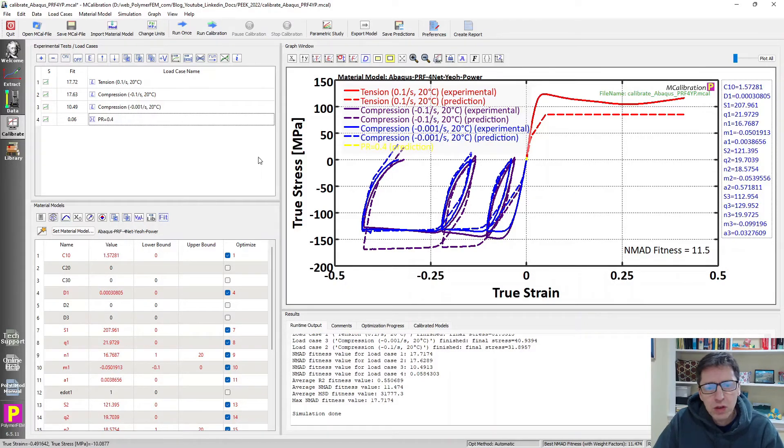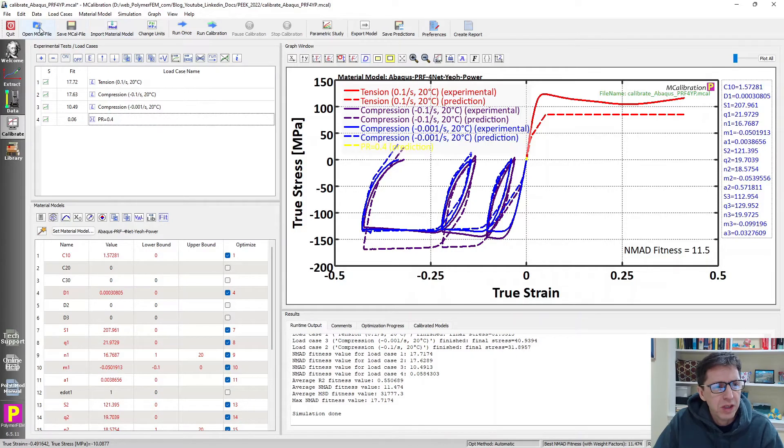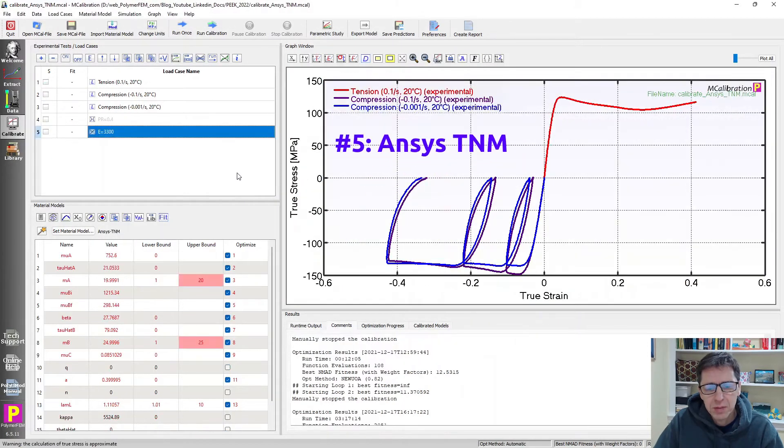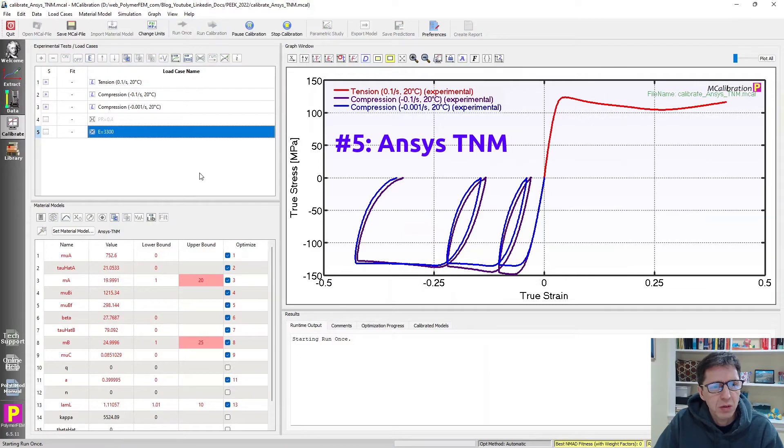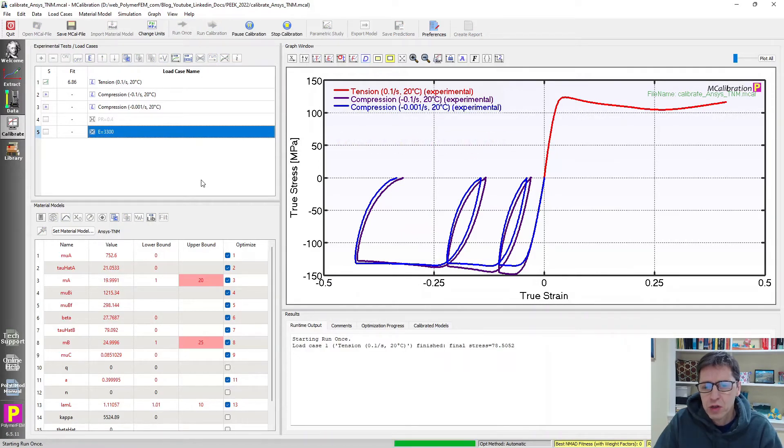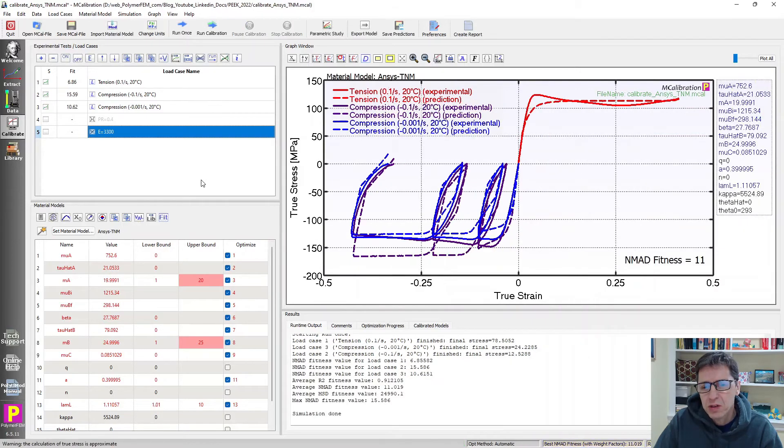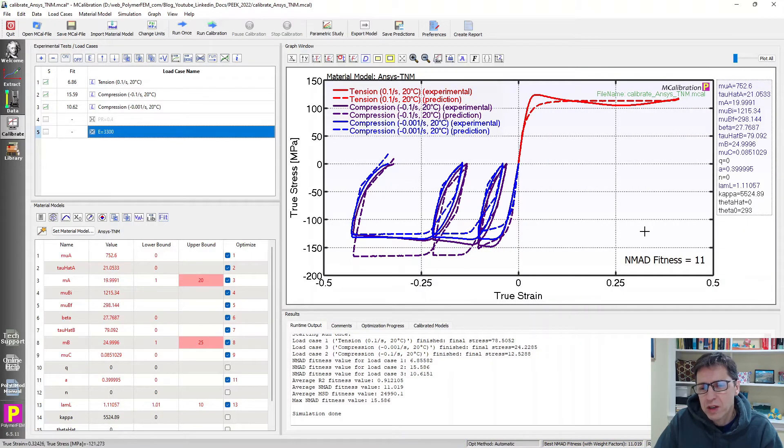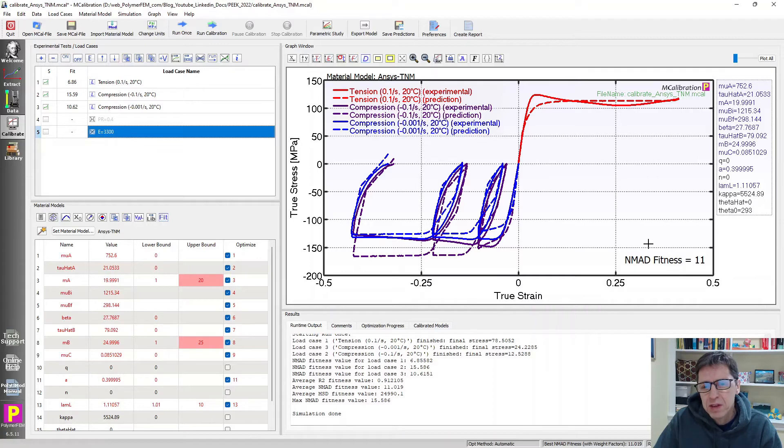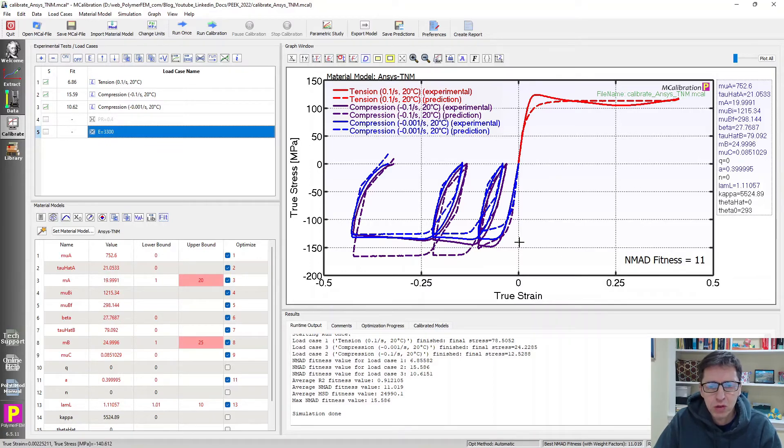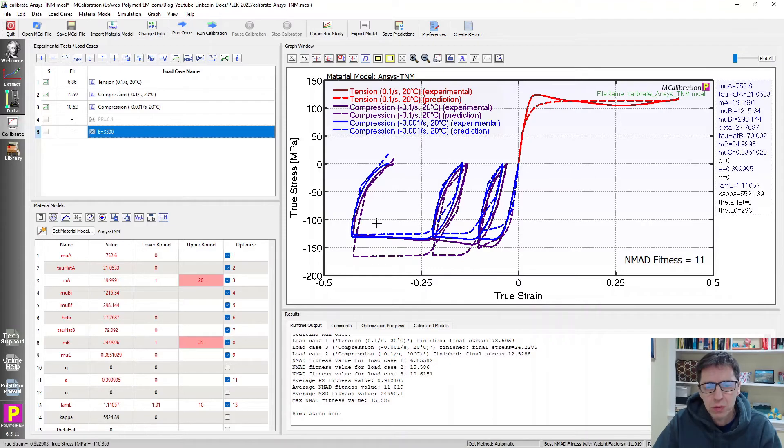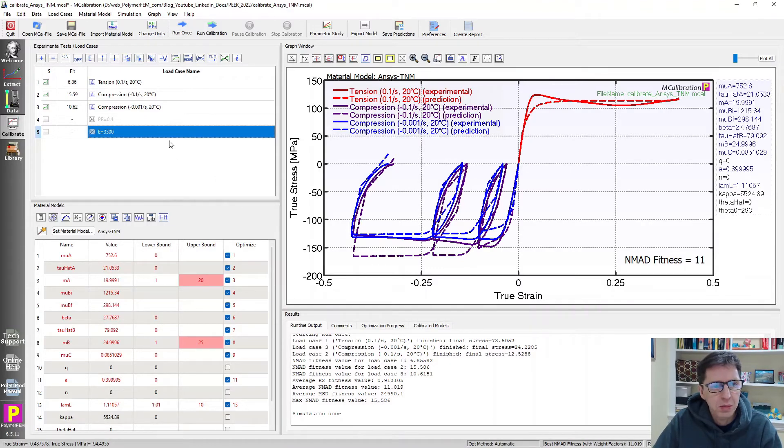We can switch over to a TNM model. So this is a model in ANSYS. Let's take a look if the ANSYS TNM model does any better. I calibrated this model. I run it once here with my already calibrated solution. And we'll see that the predictions are certainly better. Overall, the error is 11% flat now, which is perhaps okay. It's a useful prediction in this case, I would say, but we can actually do much better than this too. So this is something you can fall back to if you don't have some other idea what to do. But as I will show you, we can do even better. So this is the ANSYS TNM model.